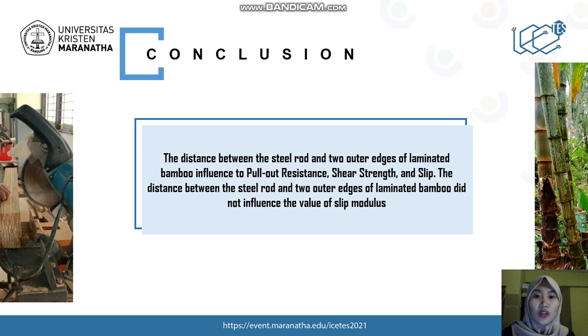We come to the conclusion for this research. The distance between the steel rod and two outer edges of laminated bamboo influenced the pull-out resistance, shear strength, and slip, but it did not influence the value of slip modulus.